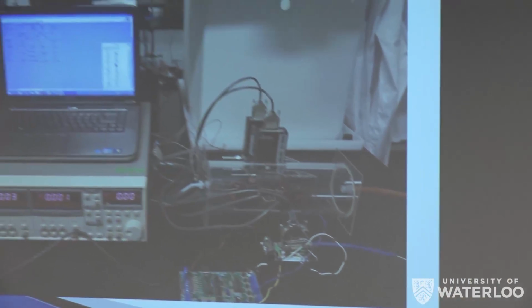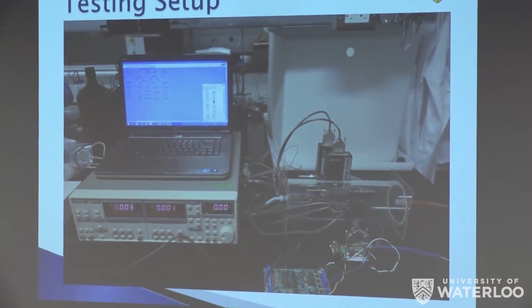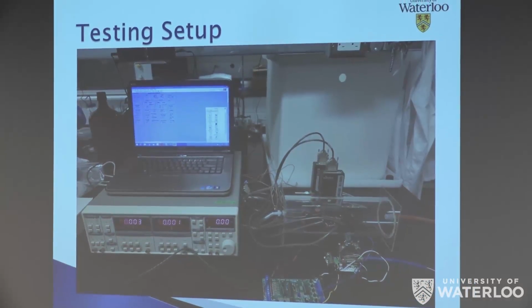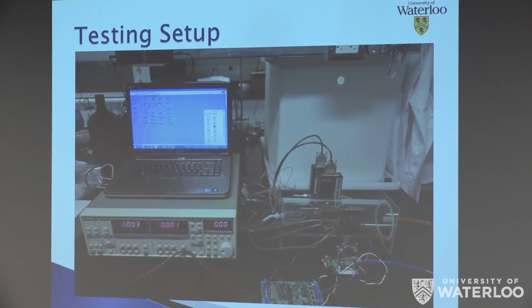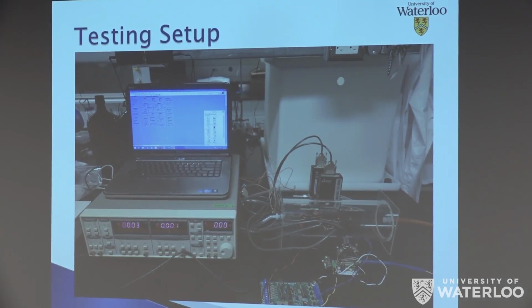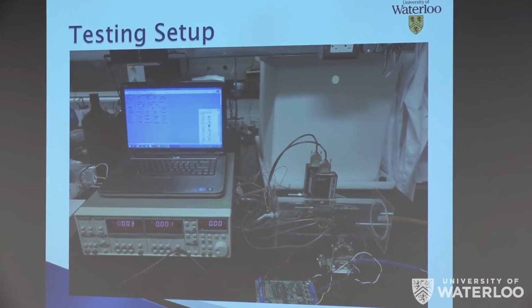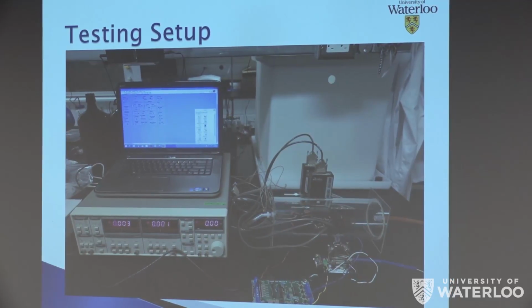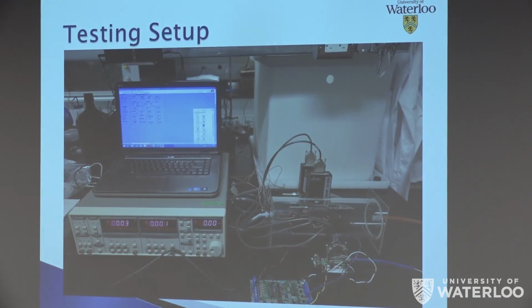This is our testing setup, which is normally in a fume hood, but we took all the components out so you can see them clearly. On the right-hand side, you can see two mass flow controllers. One is for the analyte gas, and one is for our carrier gas, which is nitrogen. You can also see our chamber fabricated, and there are two circuit boards for controlling the mass flow controllers. On the left-hand side is a lock-in amplifier, which we use to analyze our signal, and we monitor the signal using a LabVIEW program.